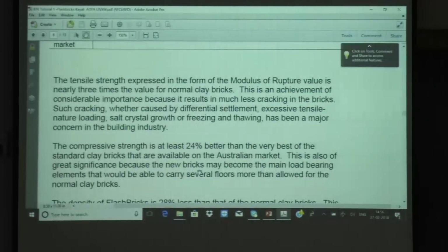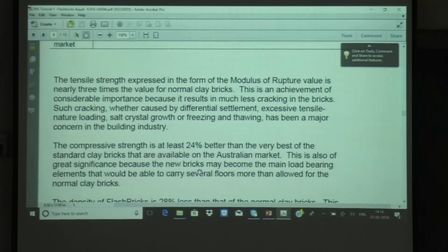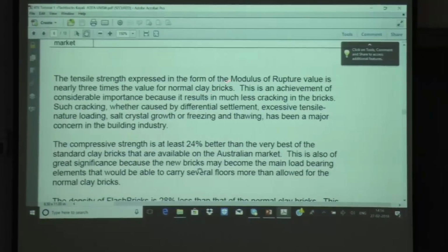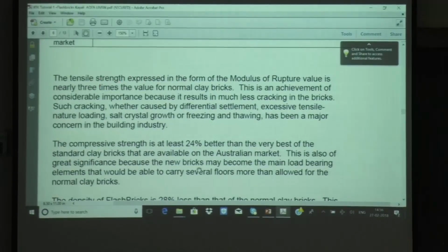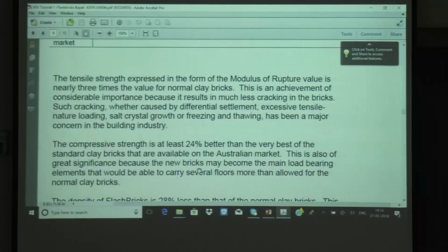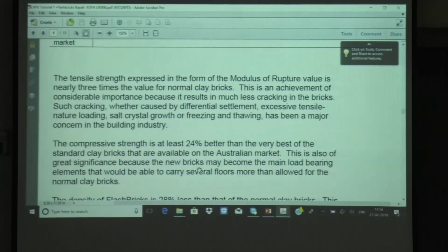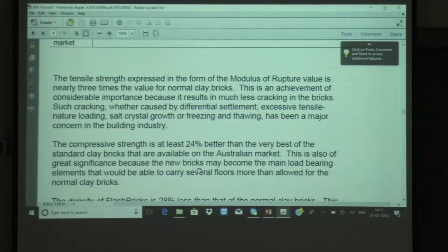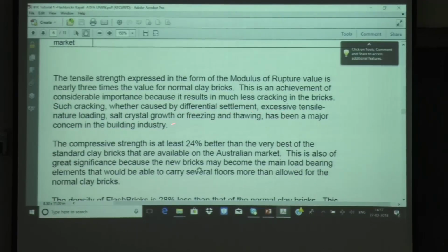Now these paragraphs explain the implication of the above properties. The tensile strength, used in the form of modulus of rupture, is nearly 3 times the value of normal bricks, depending on the range. So this is for fly ash bricks. This is an achievement of considerable importance because it results in much less cracking of the bricks. So modulus of rupture means breaking or cracking. If it has 3 times better strength, that means the fly ash bricks will crack much less. Such cracking, whether caused by differential settlement, excessive tensile nature of loading or other things, has been a major concern in the building industry. The normal brick industries always wanted better properties of the clay bricks, but it was not always possible to achieve, but the fly ash bricks showed that yes, you can do it.